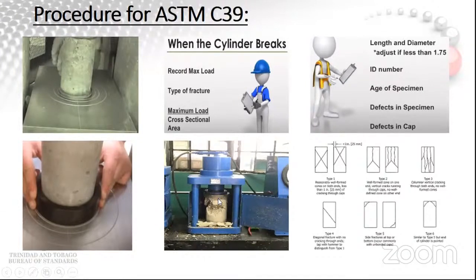A load is applied continuously without shock at a rate of movement corresponding to a stress rate of the specimen of 0.25 plus or minus 0.05 megapascals per second, or 35 plus or minus 7 psi per second. When the cylinder breaks, the maximum load, the type of fracture, and the compressive strength is recorded.